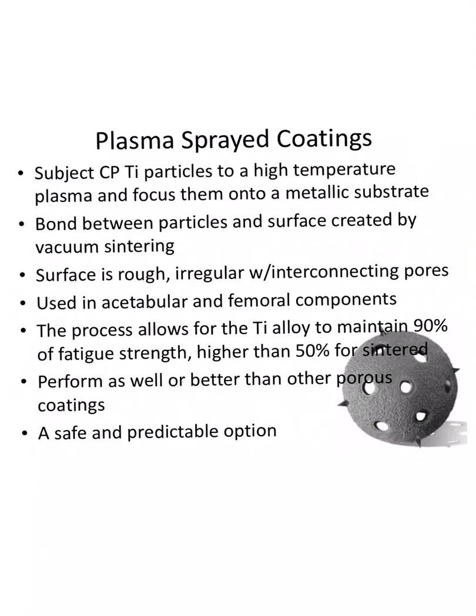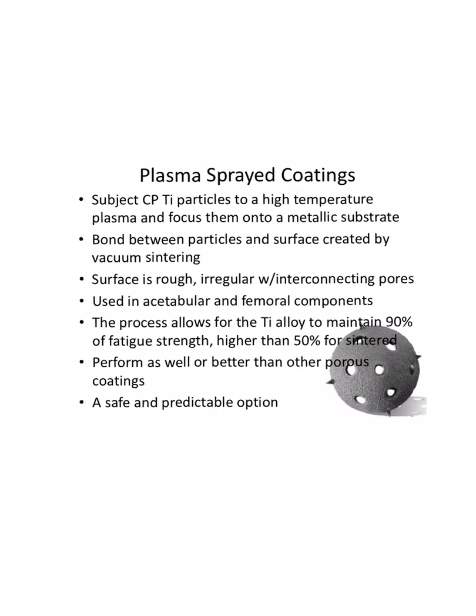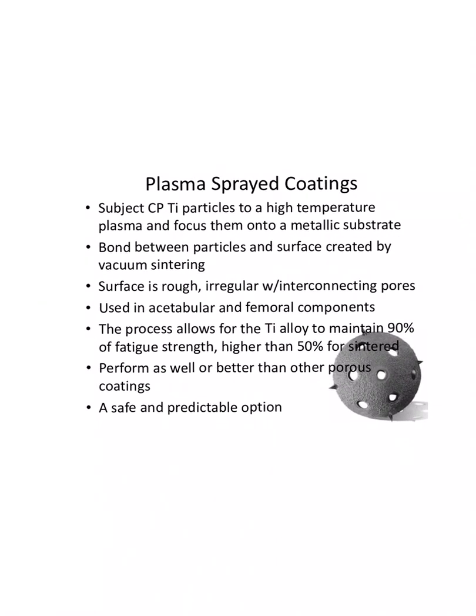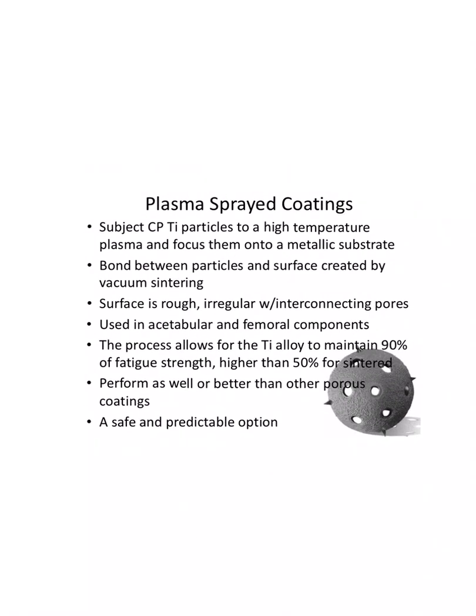And there is still this technique of plasma spraying. I talked about it for hydroxyapatite, and you can plasma spray titanium too. It melts relatively easily. At high temperature, you focus it on a metallic substrate. You can get a bond formed, and you know its story now. It's these multi-layer structures that are kind of ugly when you cut them open, but it gives you titanium where you might want it to be, and it has some porosity, irregular with interconnecting pores.